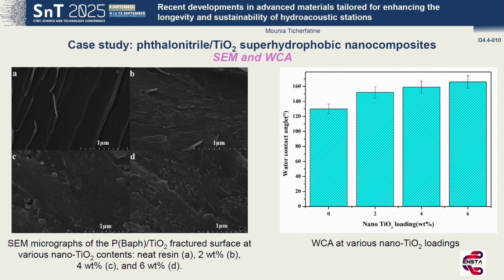Here, we performed SEM images to study the morphology of our coating. In figure A, the unfilled resin showed a smooth, featureless fracture surface morphology. On the other hand, adding these silane-treated titanium nanoparticles caused an increase in the surface roughness, and the same for all the nanocomposites shown in the 3 other images, B, C, D. The water contact angle measurement here had values over 150 degrees, which is reaching the WCA of a superhydrophobic coating.